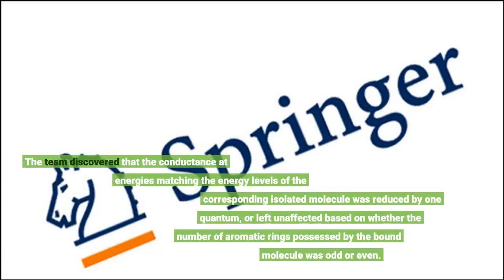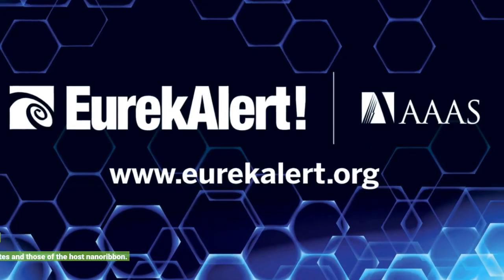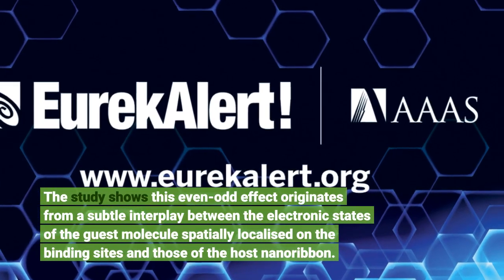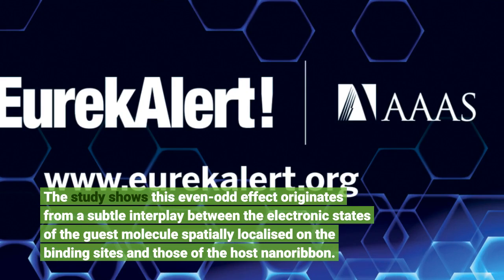The team discovered that the conductance at energies matching the energy levels of the corresponding isolated molecule was reduced by one quantum, or left unaffected, based on whether the number of aromatic rings possessed by the bound molecule was odd or even. The study shows this even-odd effect originates from a subtle interplay between the electronic states of the guest molecule spatially localized on the binding sites and those of the host nanoribbon.